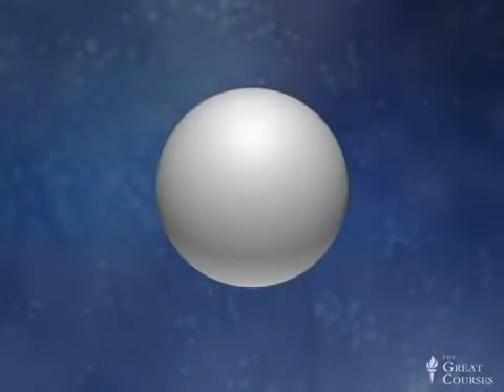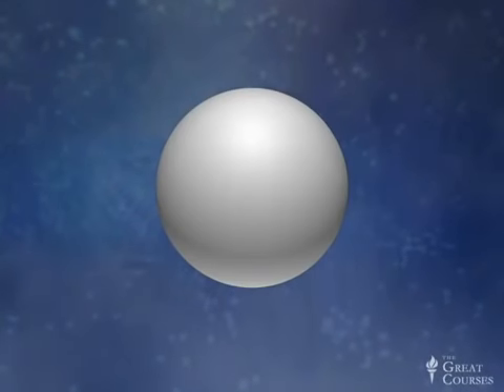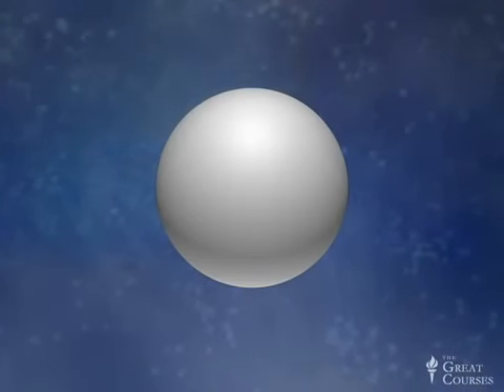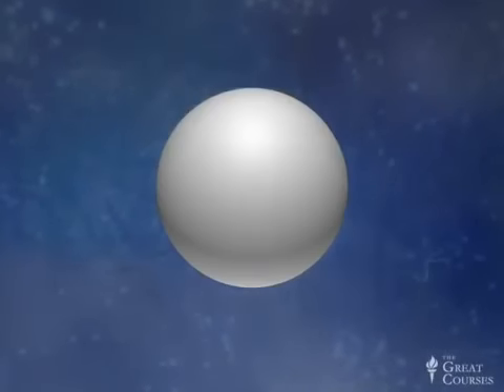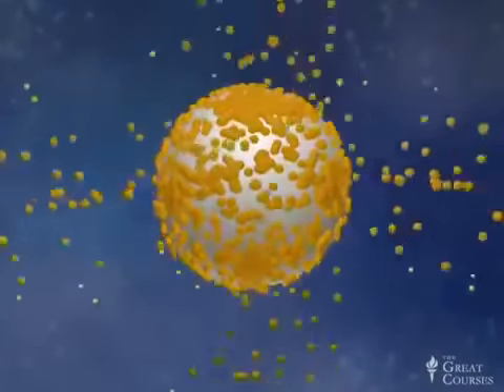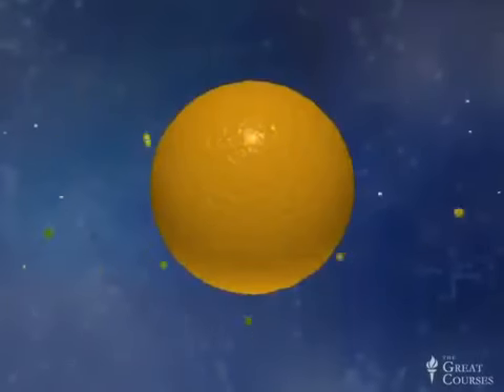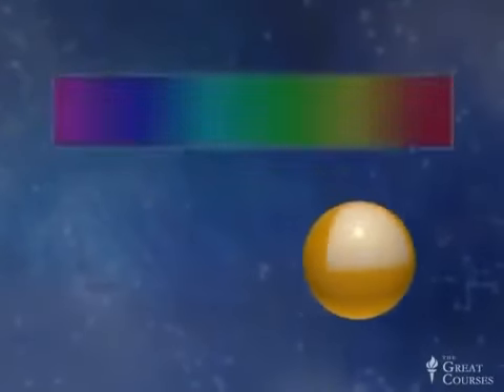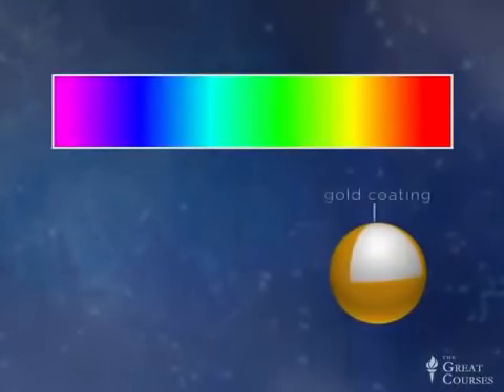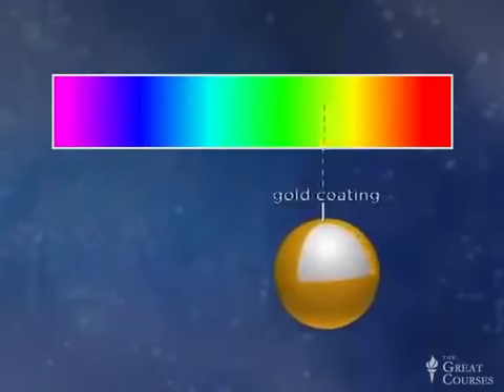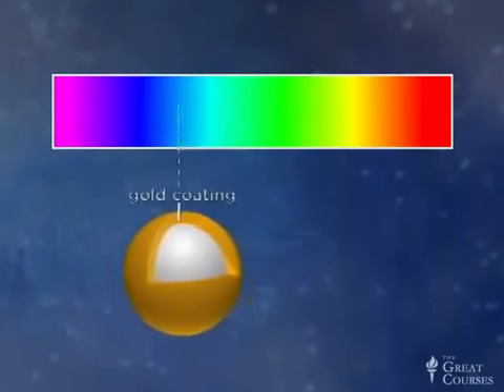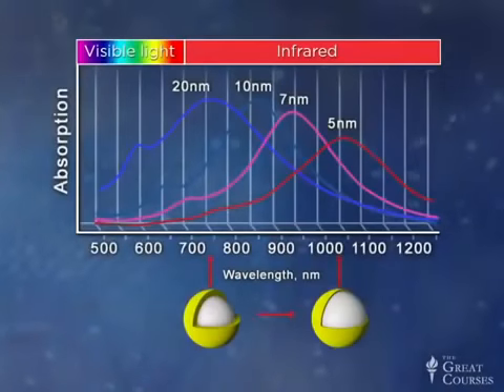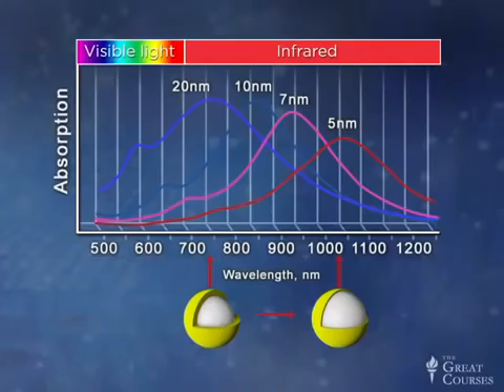So first, let's take a look at how these gold-plated nanoparticles are made. You start off with a particle composed of silica, which basically has the same composition as sand, but the particles are obviously much smaller than those that you find in sand. They then get coated with tiny particles of gold until the gold shell grows together. And what's really neat about these materials is that as the coating gets thicker, the absorption peak shifts from the more red part of the spectrum to the more blue part of the spectrum. This makes these materials very tunable. That is, the thicker the gold plating, the more the absorption peak shifts to lower wavelengths.